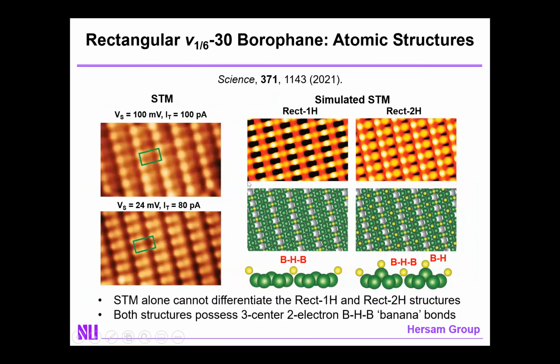Which then begs the question, where are the hydrogen atoms? And if you take STM images and compare them against simulations, you find that there are two plausible structures that are consistent with the STM data. They're both rectangular unit cells. One of them has only one hydrogen per unit cell, and the other has two per unit cell. So we'll call that rectangular 1H and rectangular 2H.